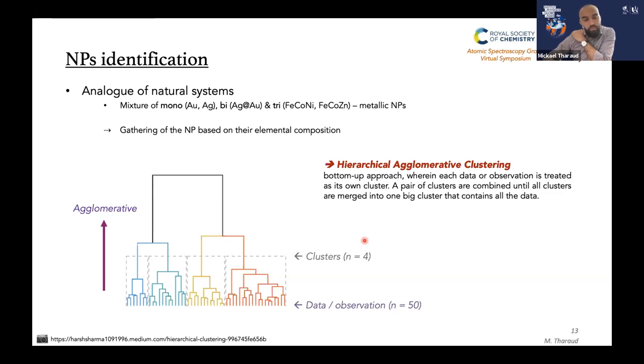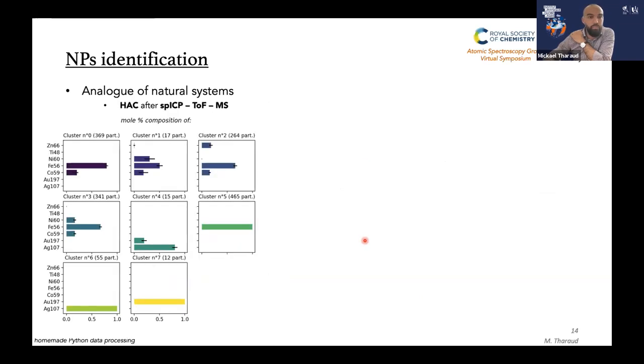But what is the result if we send our results through that kind of clustering methodology? After the acquisition using the ICP-TOF-MS, we displayed here the molar fraction composition of each of the clusters that were found. And actually, it's kind of unexpected to find 8 different clusters when you mix 5 different kinds of nanoparticles. But what is interesting is that if we look deeper into the data, we can see the five clusters that we were expecting.